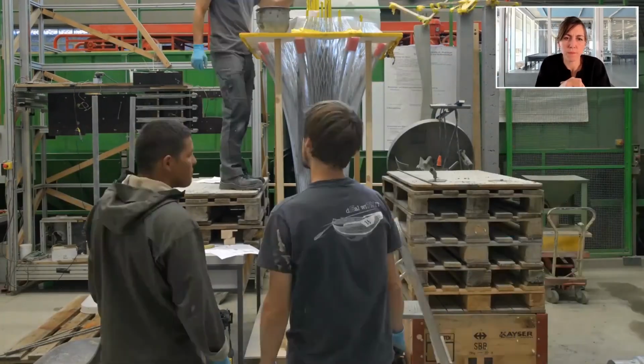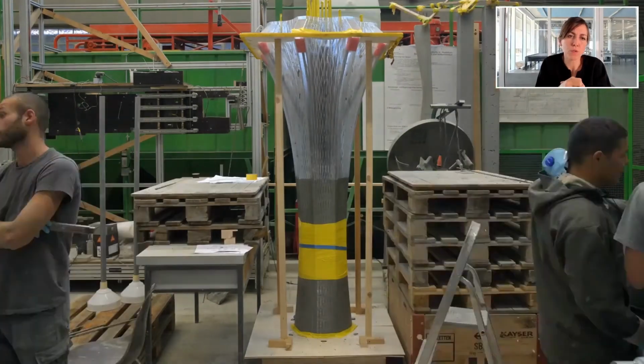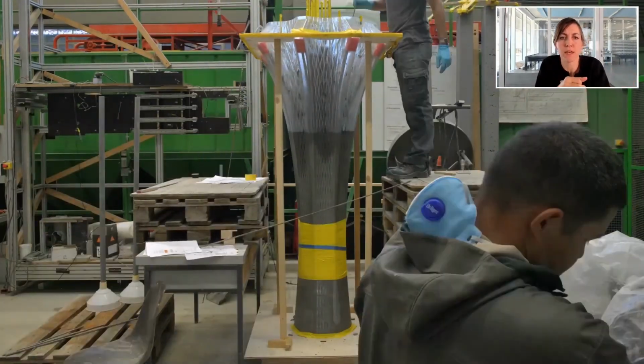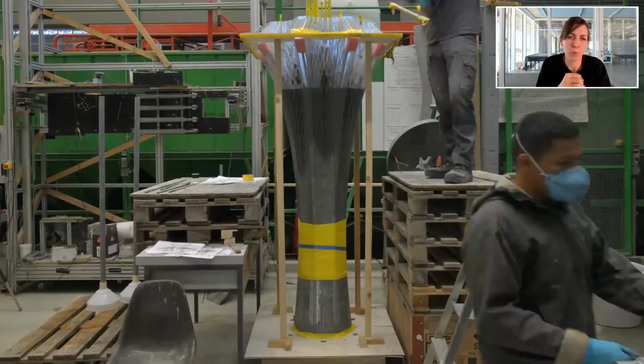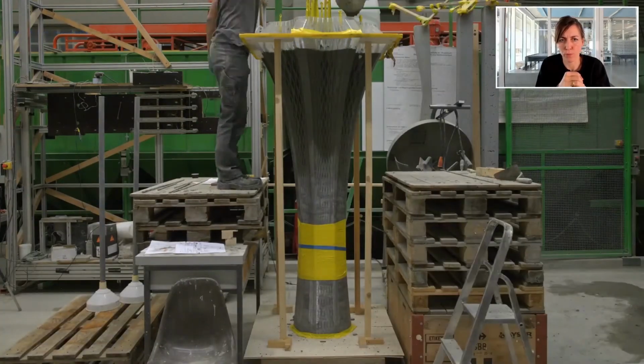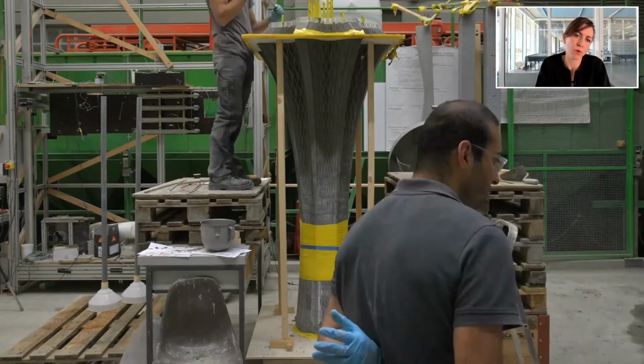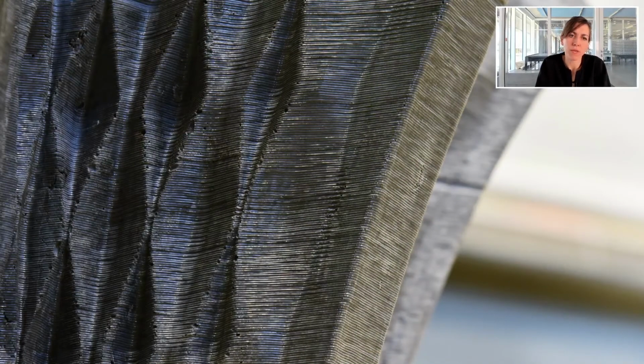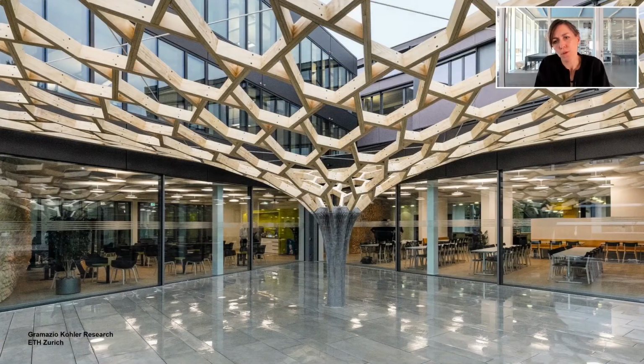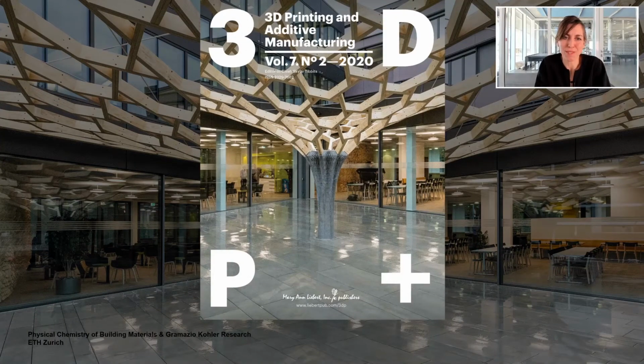So you see here the team filling up the formwork, which is only supported to assure that it's not moving around as they are filling inside. So the wooden structure that you see is not supporting any structural loads of the formwork. After the formwork was filled, the formwork is being removed. And of course we have an imprint of the 3D printed structure, but we have no cold joints and we have a beautiful surface. And the final result was then installed on site in Esslingen to provide the first built example using eggshell in a fabrication approach. And in fact, you can read more about some of the constraints that we detected during this fabrication process in the 3D Printing Additive Manufacturing Journal, where we recently published.